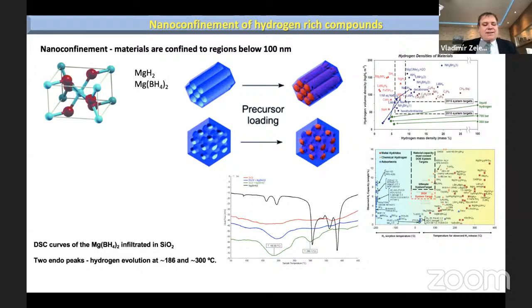So as you can see, hydrogen evolution from borohydrides is between about 186 and 300 degrees Celsius. And by nano-confinement, we are able to shift this evolution to lower temperatures. So this is the other area where we are, or these different types of materials we are starting.